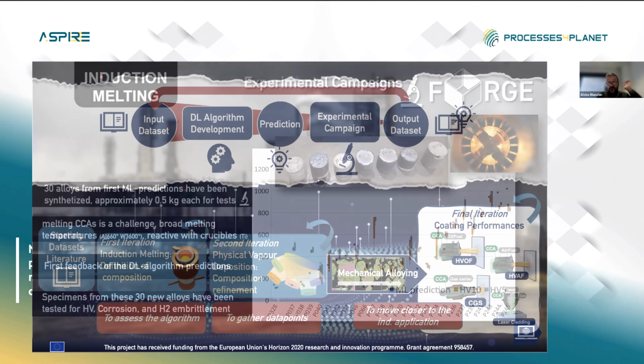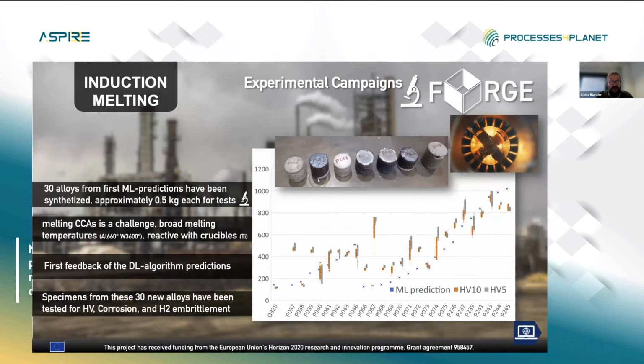So focusing a bit more on these three steps, the induction melting part has been conducted and has been very useful in assessing that the prediction of the deep learning, the machine learning algorithm, was quite good, at least in terms of trends between the composition that we chose to synthesize by induction melting and the prediction that led us to this synthesis. There are a lot of problems related to the synthesis of these alloys that are completely new. But from this set of materials, we could characterize them for hardness, corrosion, and also hydrogen uptake.